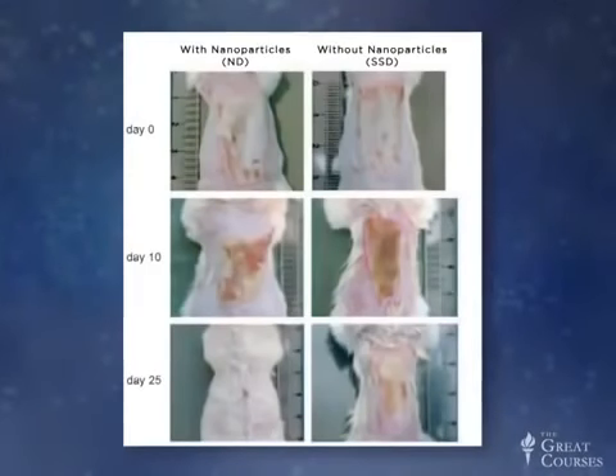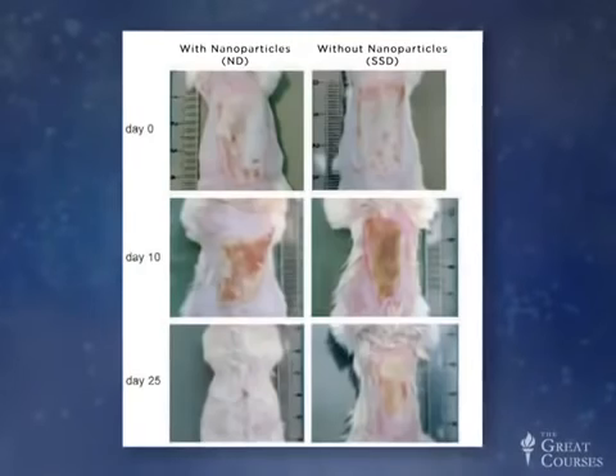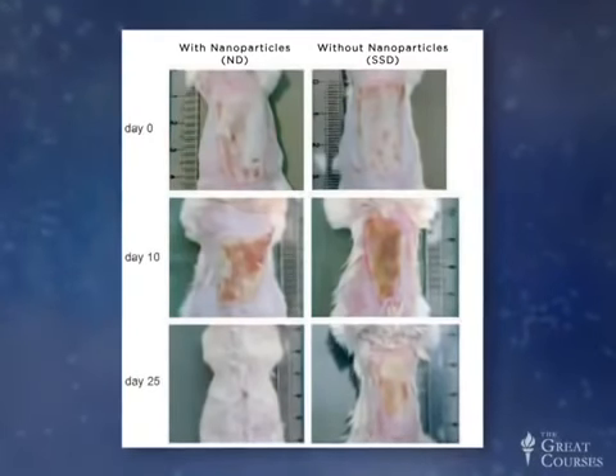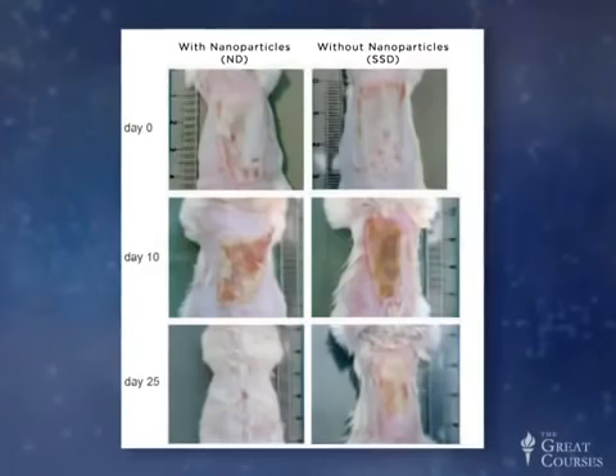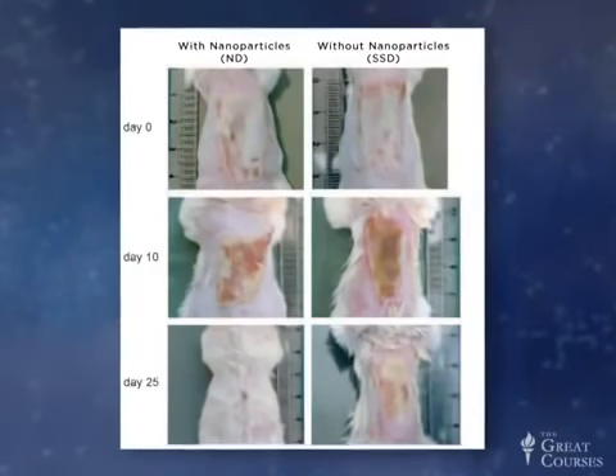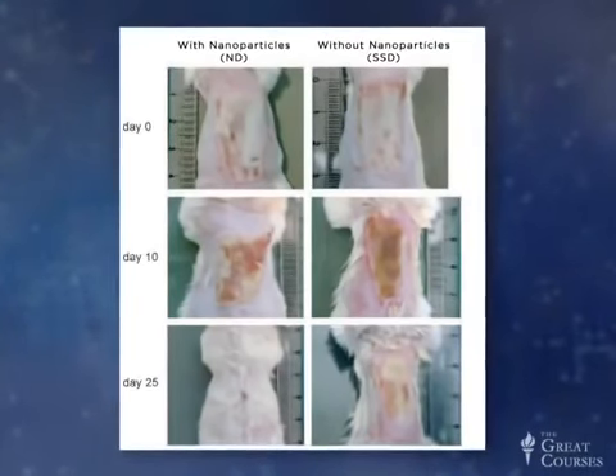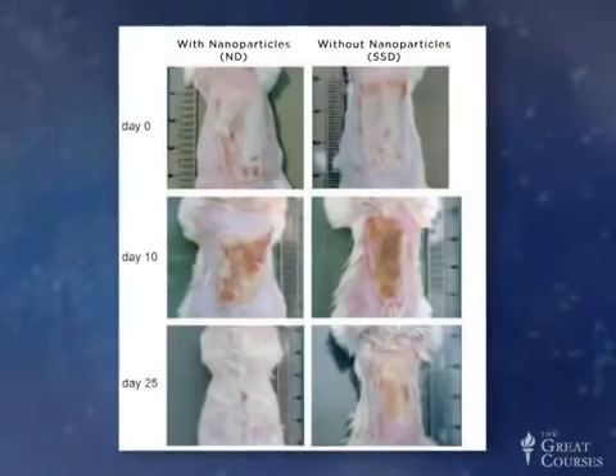This was a study where they were comparing silver nanoparticles with antibiotics, and it was discovered that burn wounds were completely healed 4 days earlier when silver nanoparticles were used. And in addition, the amount of scarring was reduced. So if you look at these images, you're looking at rats that have burn wounds on their backs. If the wounds are treated with silver nanoparticles, the rats have totally healed and regrown their fur in 25 days. Without the silver nanoparticles, you can see that the rats are still in pretty tough shape.